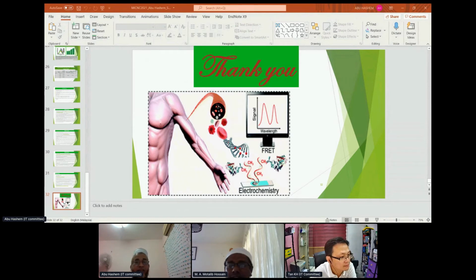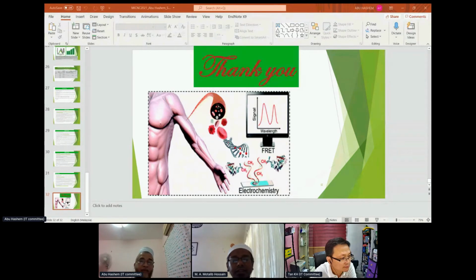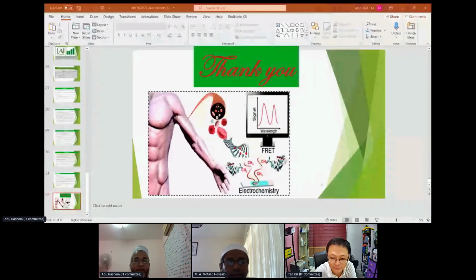I initially tried a glassy carbon electrode, but when the glassy carbon electrode is used several times with cleaning and washing, it reduces sensitivity. That is why I could not finally use it, because the result is not stable. But the screen printed carbon electrode is only for one-time use. It does not interfere with previous results, and it gives very linear output.